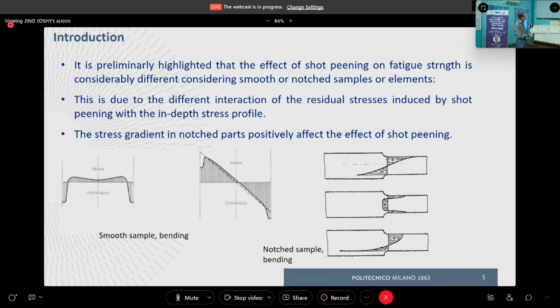But at the same time, just after the surface layer, nothing is changing, or even the stress is somehow increasing. And so this justifies the limited improvement of the fatigue strength due to the residual stress from shot peening. If we consider a notched part, we can see here there is no more the linear trend of the stresses due to bending. The gradient is deeper. Here is the residual stress trend, and we see that after the superposition of applied and residual stresses, we have a much more effective compressive residual stress. So the stress gradient in notched parts positively affects the effect of shot peening.